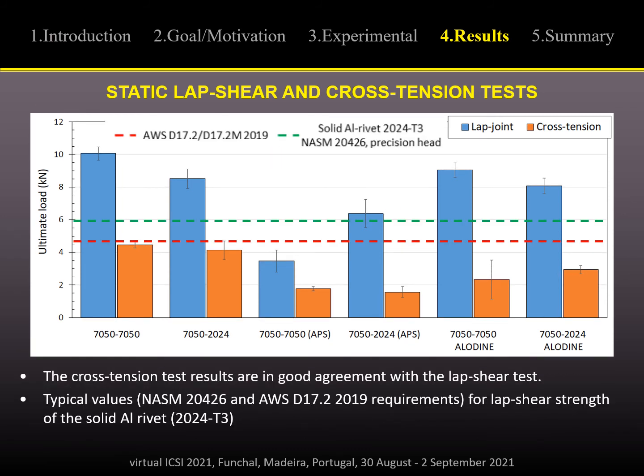And if we compare the results with the requirements or specification from the Aerospace Industries Association and American Welding Society for the lap shear strength of the solid aluminum rivet 2024 in T3 state, we can see that the bare configurations and the primer-free configurations have no problem meeting these requirement values, whilst these 2 configurations with primer have problems meeting the requirements of this specification.